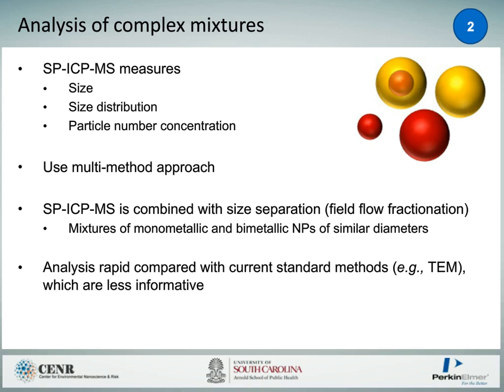Single-particle ICP-MS measures size distribution and particle number concentration. We used a multi-method approach. So in this study, we used field flow fractionation to separate our particles, which were mixtures of monometallic and bimetallic particles of the same diameters. And then we showed that this was a rapid technique compared to having to do TEM analysis.